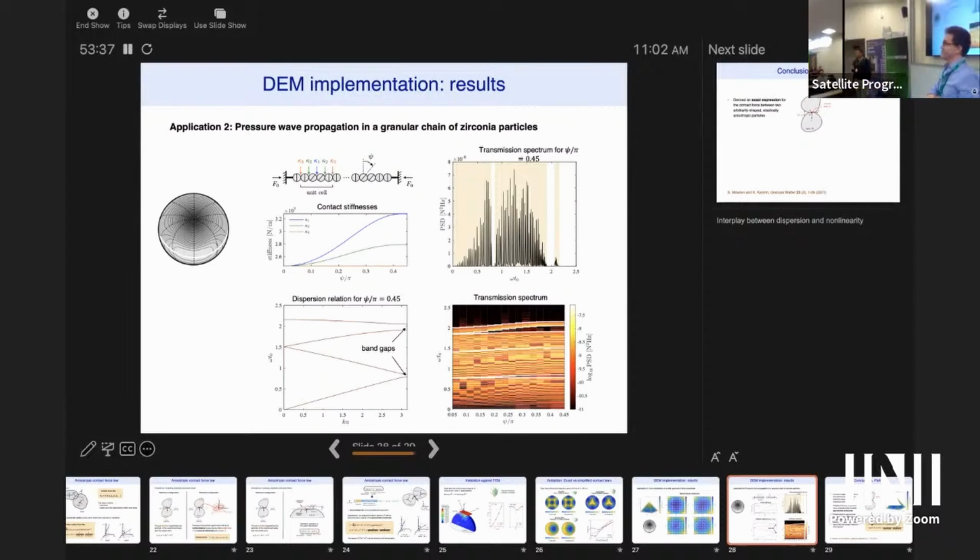I have no idea. I mean, if you have a whole set of frequencies you want to filter out, the more constraints you give it, of course, the fewer solutions there should be. But if your unit cell could be arbitrarily large, you could probably filter out anything, right? Yeah, you could have multiple angles of tilt. In the end, it's actually not that bad, because once you pre-stress a string of beads, then it goes back to being a linear acoustic problem again. Because that 3/2 power only really matters when delta is very close to 0. So if you pre-compress it, it's locally linear. So you can actually use linear techniques to get these band gap diagrams.